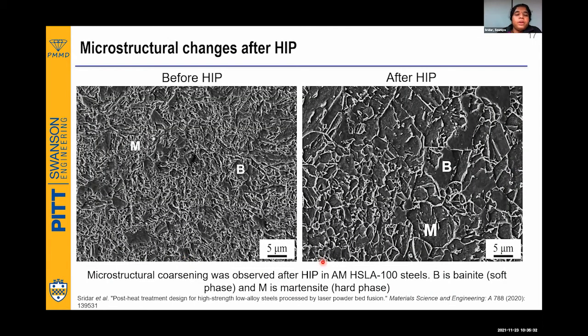This is the before-HIP microstructure, and this is the after-HIP microstructure. These are SEM micrographs, and you see that there are two types of phases here: one with surface relief and one without surface relief. The one with surface relief is the martensite, which you can take as the hard phase. The one without surface relief is the bainite, which is the soft phase. You see how fine it is here, but after I apply HIP, my bainite is growing and my martensite has become huge and so on.